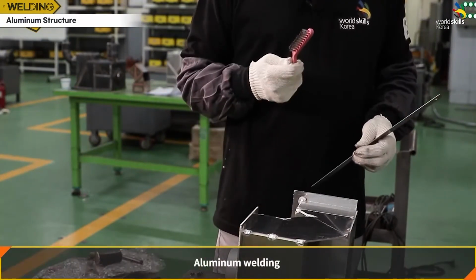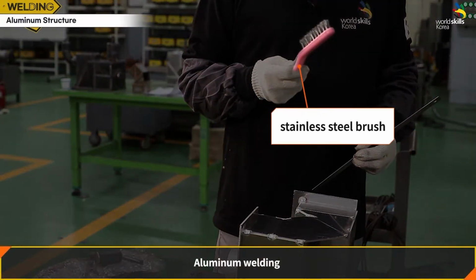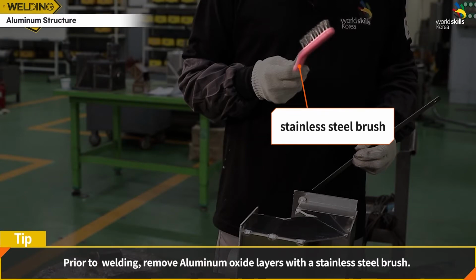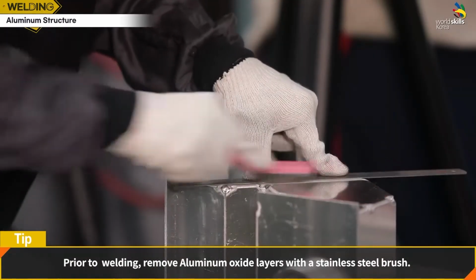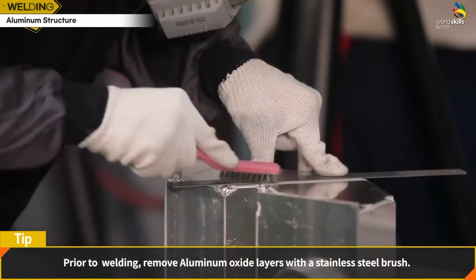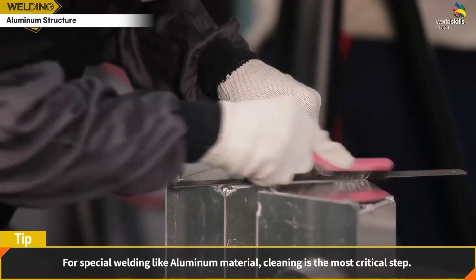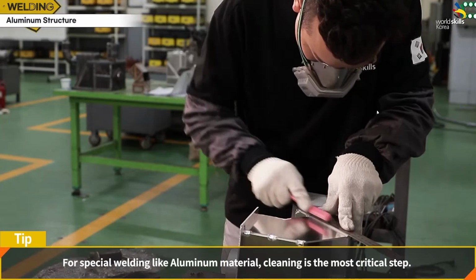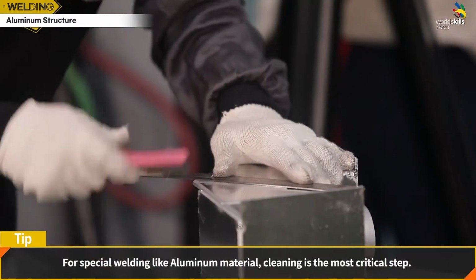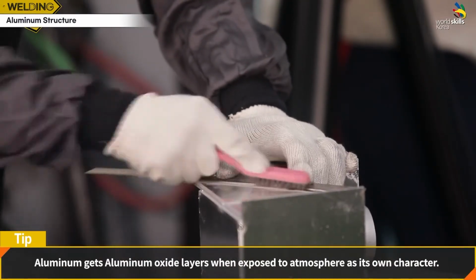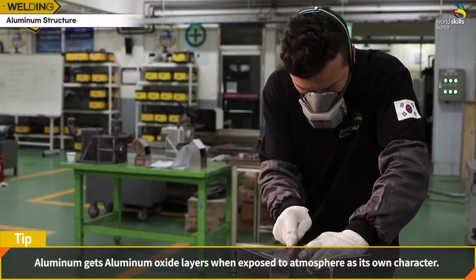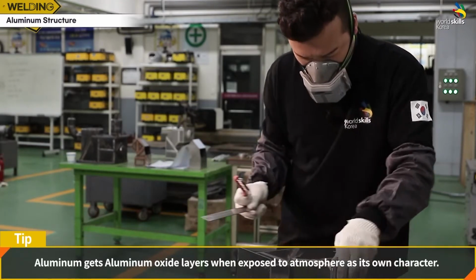Aluminum welding. Prior to welding, remove aluminum oxide layers with a stainless steel brush. For special welding like aluminum material, cleaning is the most critical step. Aluminum gets oxide layers when exposed to air as its own characteristic.